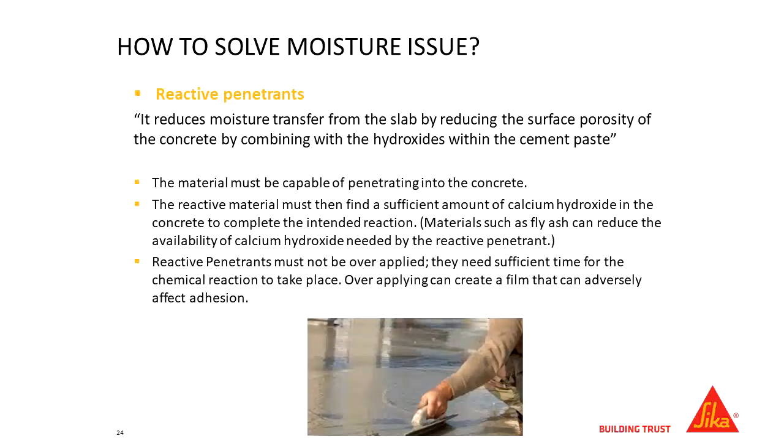It takes sufficient time for this chemical reaction to take place and for those pores to close up. And over-applying can create a film that can adversely affect adhesion. So the problem with some of those reactive penetrants is if they're not installed exactly perfectly, they leave a film that now you've created another problem. So you've solved the problem with the moisture, but you've created a problem because now your adhesive won't stick to it, which is why, for a slab that is going to be covered with finished goods, they typically don't like to use these reactive penetrants because it can affect the adhesion.